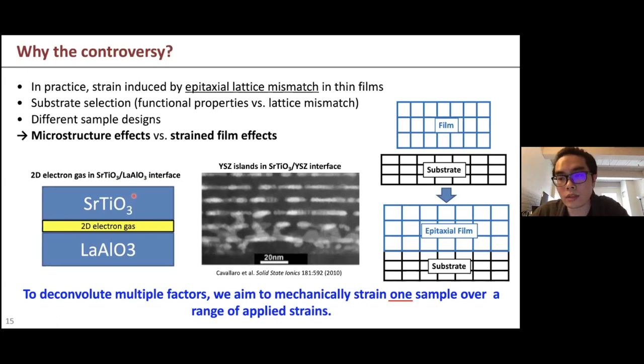So meaning that even though we might have dislocations or all those kinds of defects in the beginning, if we can just apply the strain on one sample and then measure the conductivity along with the strain, we have the same starting point. So we don't really have to care about sample to sample difference or these different substrate differences. Because when you apply different strain on the same thin film in this technique, you don't have to use different kinds of substrates.